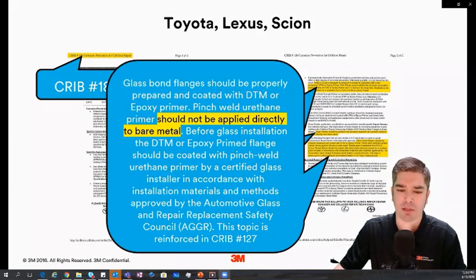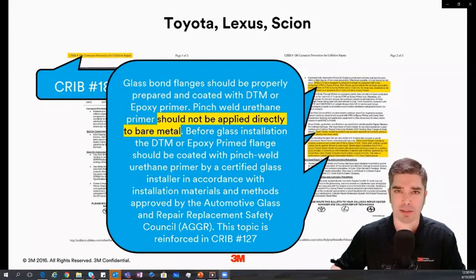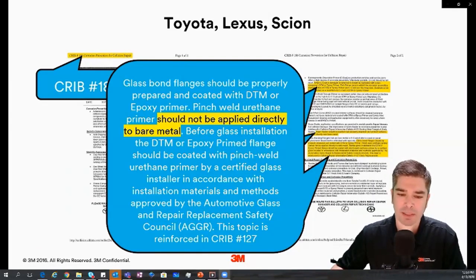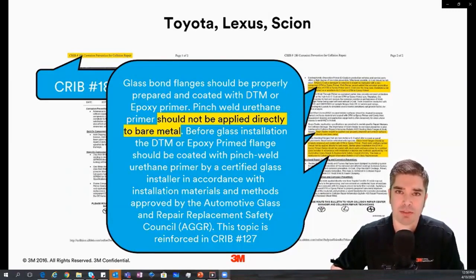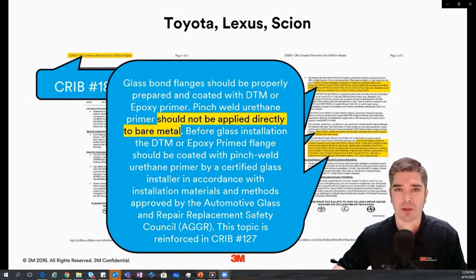And then one more thing to highlight quickly is that when it comes to bonding in glass and glass-bonded flanges, they're talking here that bare metal pinch-weld urethane should not be used, okay? They want it to be put over an epoxy primer as well. So if you're using a product that's approved for direct-to-metal, when it comes to primers and windshield urethanes, we want to make sure that we're always going to defer to the OEMs, right? They're the experts on how the vehicle was originally constructed and should be reconstructed in the event of an accident. So they're always going to supersede whatever the product manufacturer's recommendations are. At 3M, we work together with the OEMs to come up with our best practices that align with the OEMs, and that's what we're going to dive into here a little bit more today as we go through this exercise.